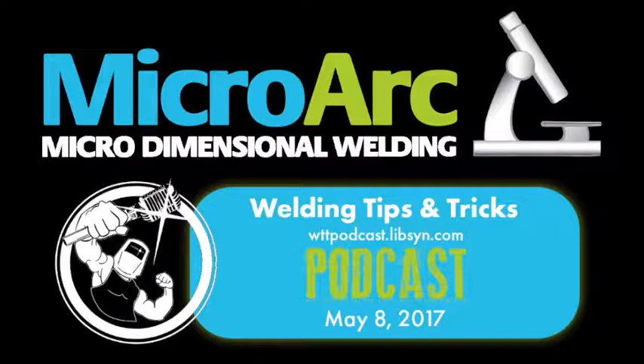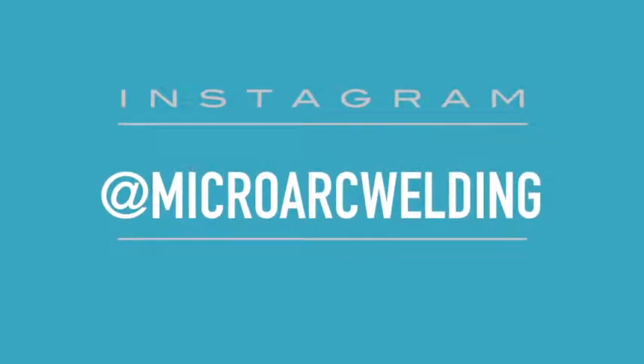Okay. And when we start an arc, we can have that. Like, I just bought a Dynasty 400. I saw that. Yeah, and we just set it up last week. This is because we do some big stuff too. We don't use this for micro welding. But it has a very nice, once you get the arc started, it comes down low very nicely for what we do. But when the arc starts, it's like a 5 amp surge. And that's actually too much for what we do. So I might see if I can get somebody from Miller to see if they can tweak that for us. But yeah, we use 16th a lot.